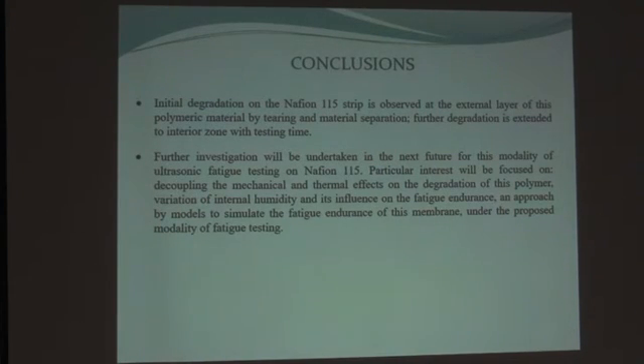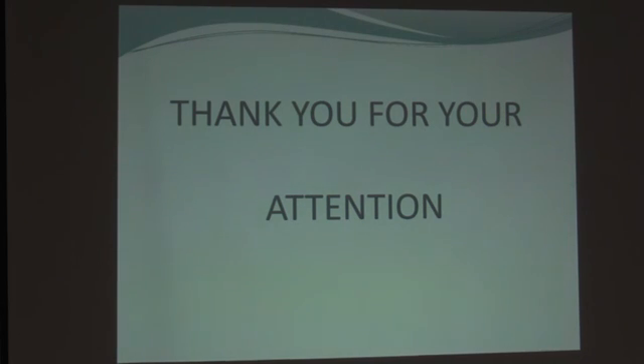Finally, initial degradation on the Nafion 115 strip is observed at the external layer of this polymeric material by tearing and material separation. Further degradation extends to the interior zone with testing time. Further investigation will be undertaken in the near future for this modality of ultrasonic fatigue testing. Particular interest will be focused on decoupling the mechanical and thermal effects of the degradation of this polymer, variation of internal humidity and its influence on the fatigue endurance, and a theoretical approach by models to simulate the fatigue endurance of this membrane under the proposed modality of fatigue testing. Thank you for your attention.